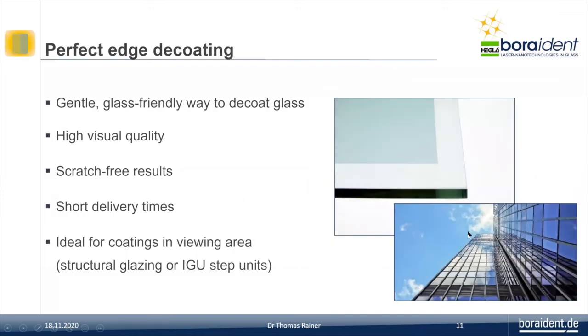The fourth example I have to show you is from the field of architectural glass. Sometimes we have facades, so-called structural glazing. There is usage of a so-called step IGU unit. That means one pane of this step IGU unit is larger, and there's a need to remove the low-E or sun protective coating at the edge in a wide range, 50 millimeters up to 100, 200 millimeters, to then bring ceramic color on it and clamp on this region the whole glass product in the facade.